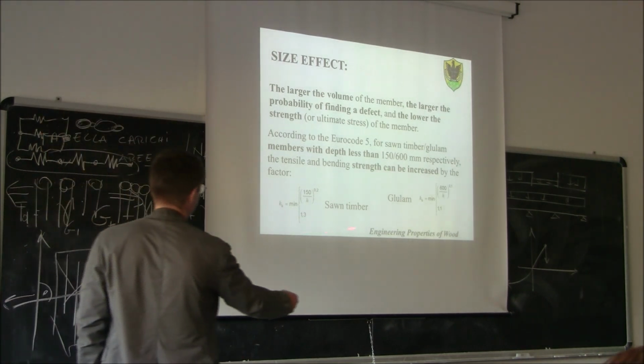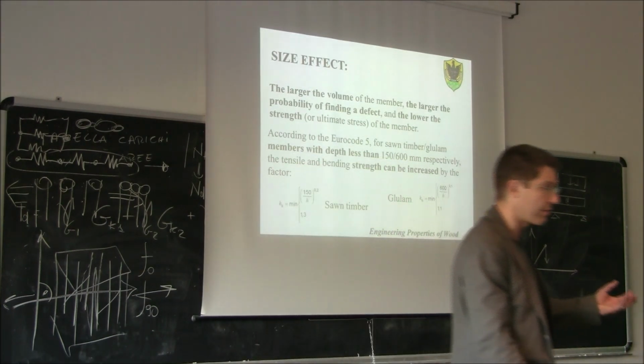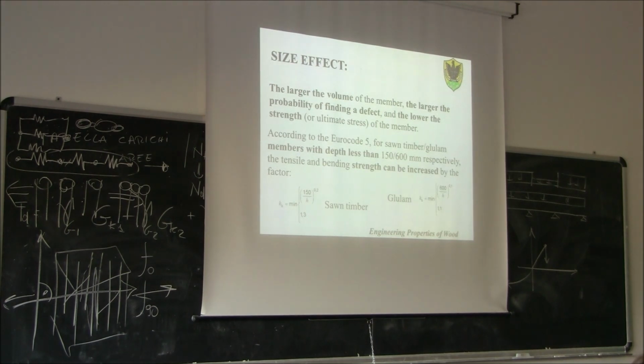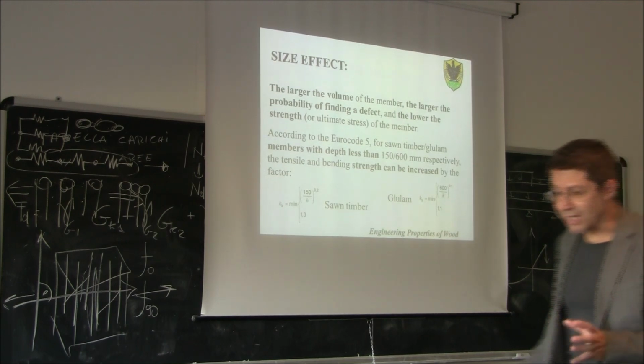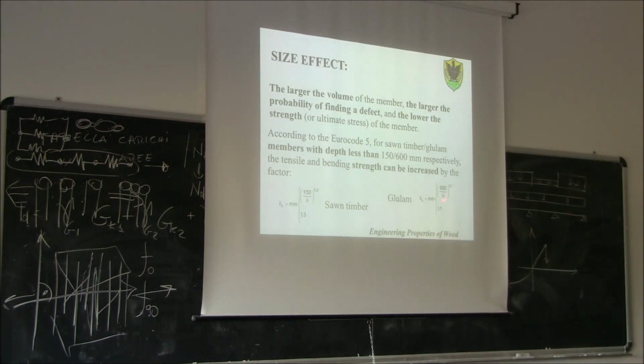So this is taken into account by the regulation, for example by Eurocode 5, when it comes to calculating the strength of the material. There is a coefficient called kh, which takes into account the size of the cross-section. The normal standard size of sawn timber is considered 150 millimeters, while the normal standard size of glue-laminated timber, legno lamellare incollato, is 600 millimeters. So the regulation says if you have the normal size of sawn timber or glulam or a larger size, then kh is equal to 1. But if you have a size smaller than the normal size, for example less than 150 millimeters, or less than 600 millimeters, then you can increase the strength with this coefficient. For sawn timber it may get up to 1.3, for glulam just 10%, up to 1.1.